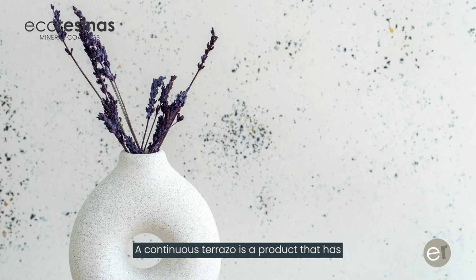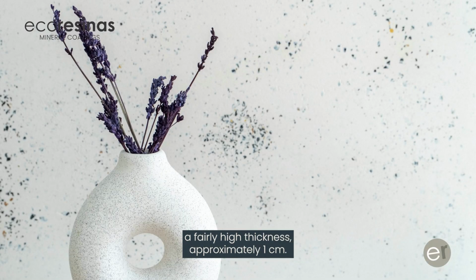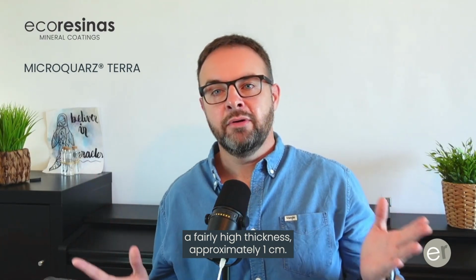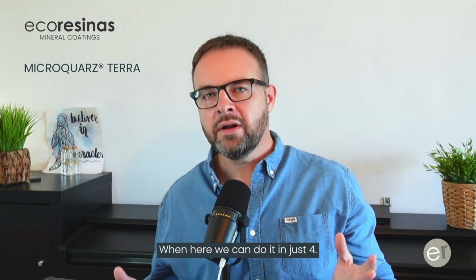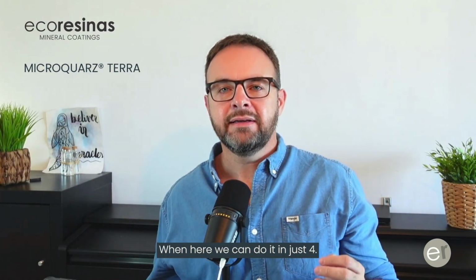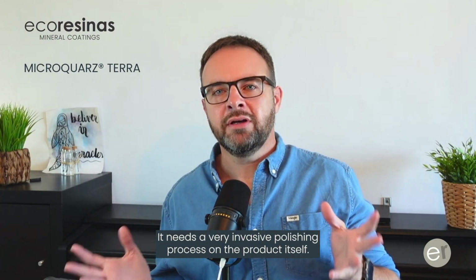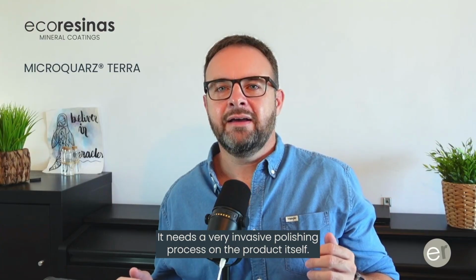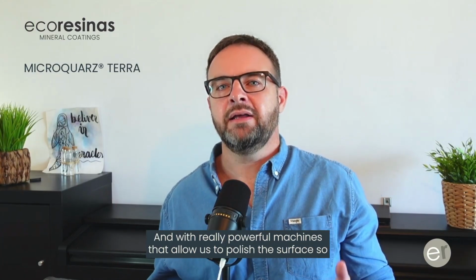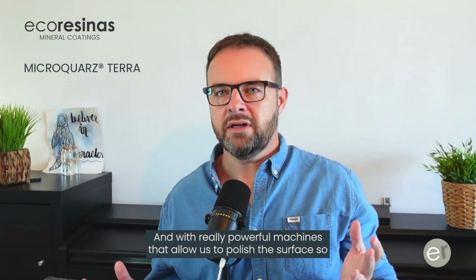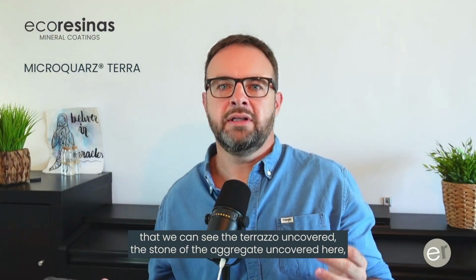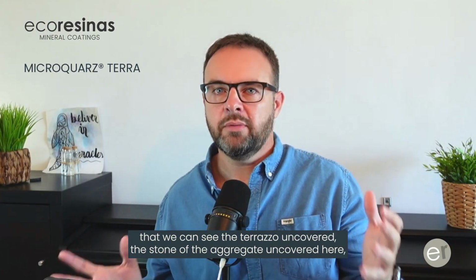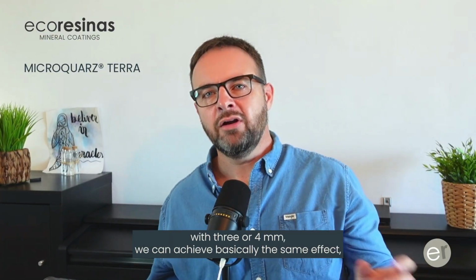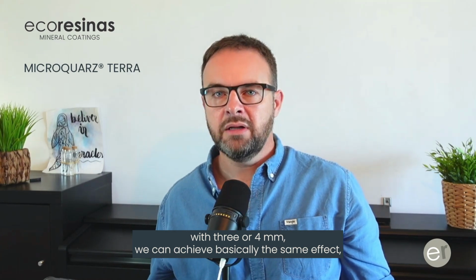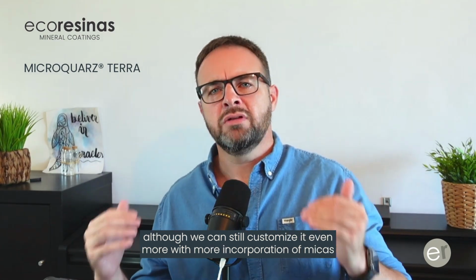A continuous terrazzo is a product that has a fairly high thickness, approximately 1 centimeter, when here we can do it in just 4 millimeters, and it needs a very invasive polishing process on the product itself and with really powerful machines that allow us to polish the surface so that we can see the terrazzo uncovered, the stone of the aggregate uncovered. Here with 3 or 4 millimeters we can achieve basically the same effect, although we can still